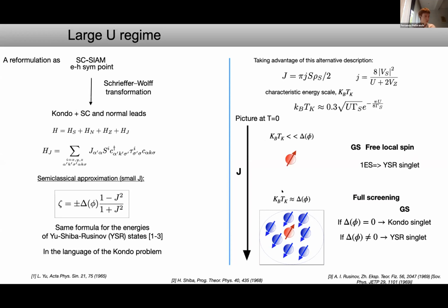However, when we go to a regime in which k_B T_K is of the order of the pairing, the ground state changes due to the full screening of the local spin. If the gap is exactly zero, this gives rise to Kondo singlets, and if it is finite, it gives rise to YSR singlets.